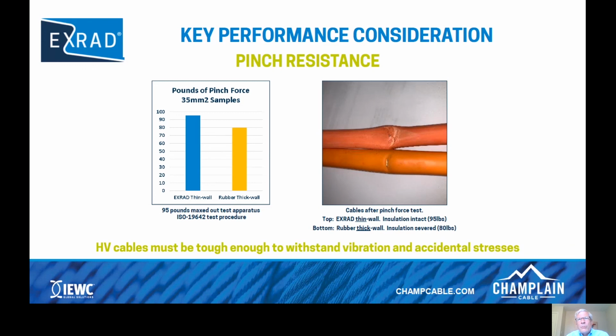Pinch is another parameter that we do testing on. Here again, we tested an X-Rad thin wall compared to a rubber thick wall. In this case, the rubber thick wall was able to withstand 80 pounds of force before breaking through to the conductor. Unfortunately, our equipment only reached 95 pounds, so we recorded 95 pounds on the thin wall, and that maxed out our equipment, so we're not sure exactly how much more pressure it would take before failure. Important takeaway: high voltage cables must be tough enough to withstand vibration and accidental stresses.